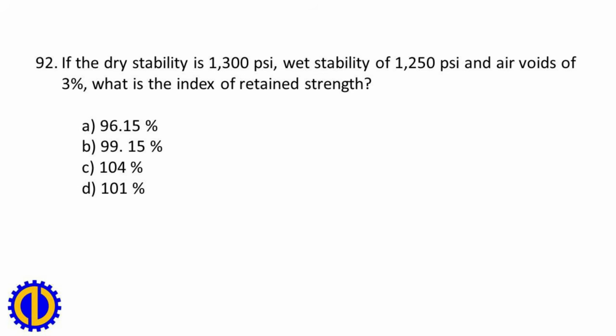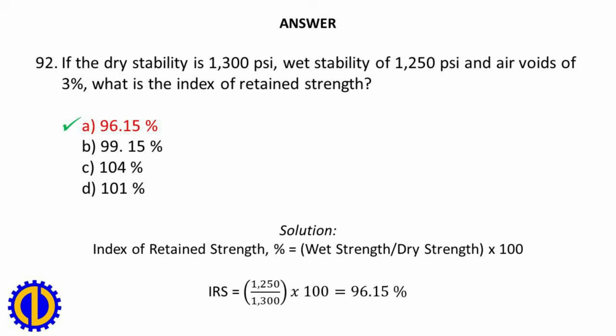92. If the dry stability is 1,300 pounds per square inch, wet stability of 1,250 pounds per square inch and air voids of 3%, what is the index of retained strength? A. 96.15%. B. 99.15%. C. 104%. D. 101%. A. 96.15%. Solution: index of retained strength equals wet strength divided by dry strength times 100.